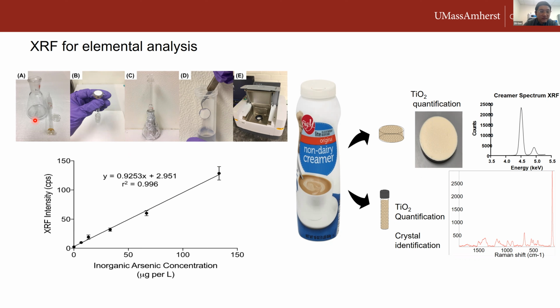In this case, the arsenic is being converted into arsenic gas and collected by this filter. So by analyzing this filter, we can establish very good calculations. And on the right-hand side, similarly, titanium dioxide can be measured directly from the non-dairy creamer when it's pressed into pellets. Also, we can use Raman spectroscopy to identify the crystal forms of different titaniums.